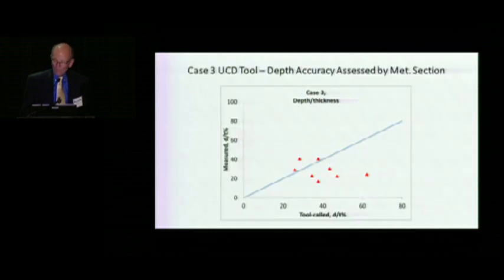One of the best ways that we found that when people calibrated what the ILI was doing was to either grind down to the bottoms of defects to really discover the depth, or to do metallographic section. And when you do that sort of thing, then the tool calls start to look a little better. And in most cases, at least in this one case 3, the tool was overcalling the defect. So that's a good result. Bearing in mind that there were still those large defects that cause service failures that cause us concern.